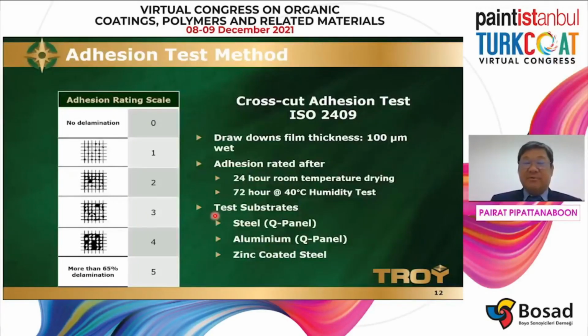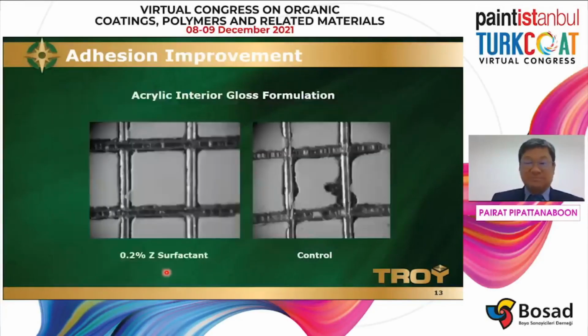For the adhesion test method, we follow ISO 2409, the cross-cut adhesion test. The adhesion is tested on steel, aluminum, and also zinc coated steel. The coating is applied at 100 micron, with 1 day room temperature drying, followed by 3 days at 40 Celsius humidity test. The ranking is from 0 or 1, which is no delamination after the cross-cut adhesion test, to 4 or 5, which is 65% or more delamination after the cross-cut. And this is what you get from the acrylic interior gloss formulation.